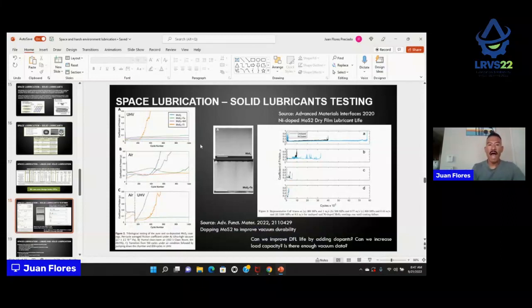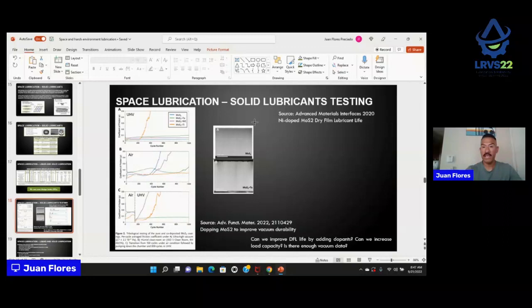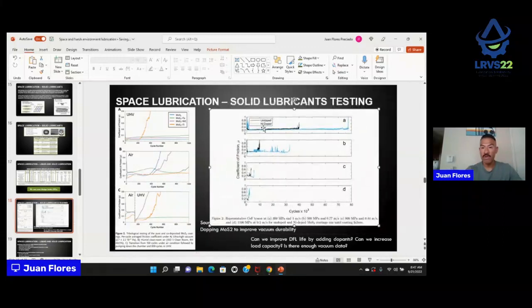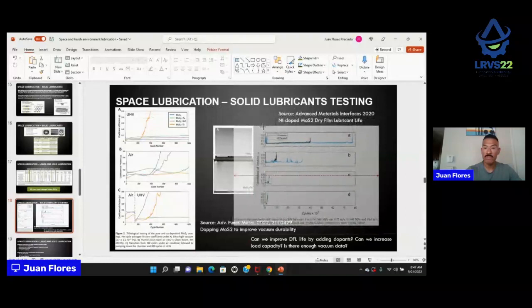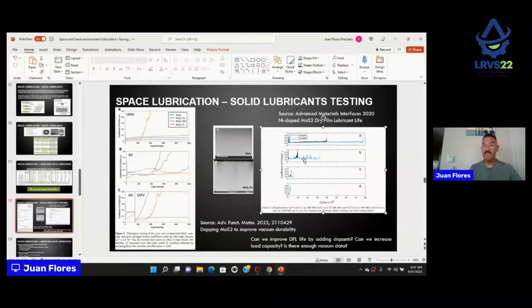This is another clear example of what happens. Sometimes we can also dope our solid lubricant to increase some of the properties, right? Like for instance, this study that you can see right here, they use nickel on the molybdenum sulfide to improve the load carrying capabilities. But they also realize, this is friction versus distance, that they increase the life of the molybdenum sulfide, right? The undoped is the black one, the doped is the blue one. So they reduce friction a little bit, but also extend the life of the lubricant. So that's something very important for me, especially if I can remove or replenish the lubricant in space, right?